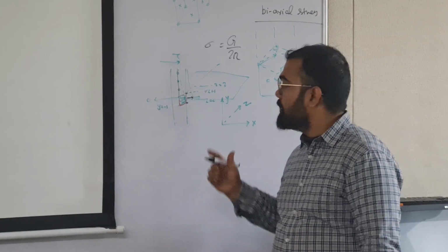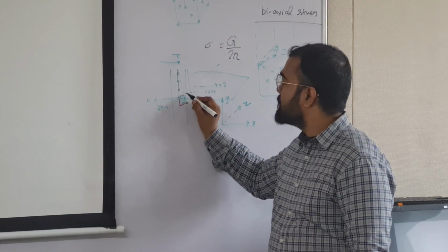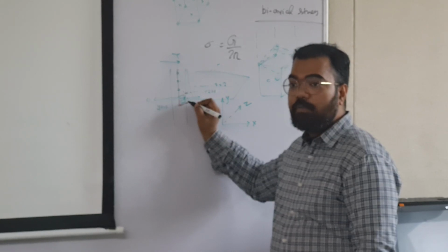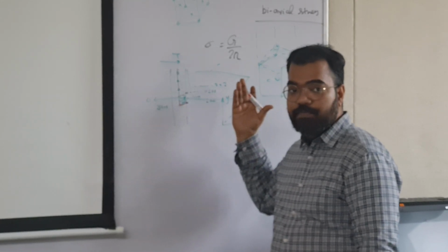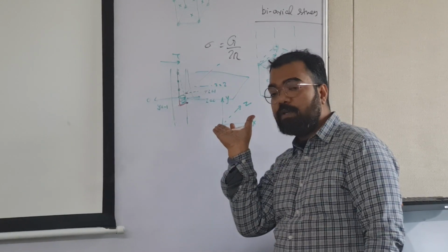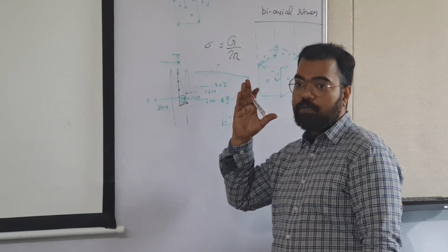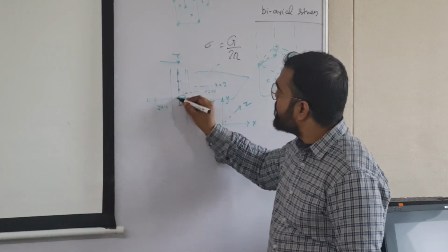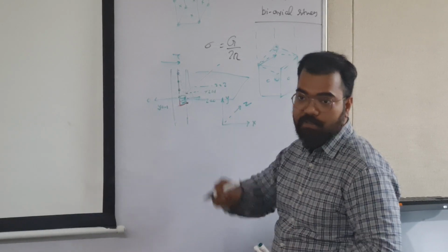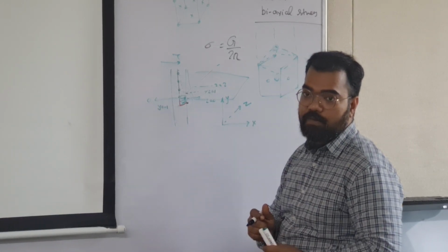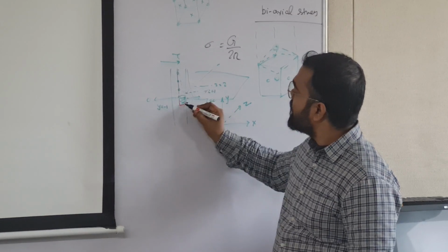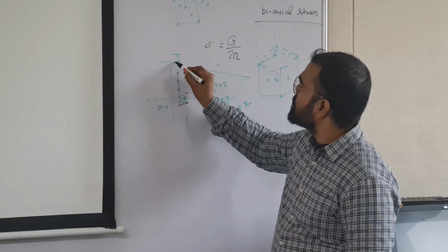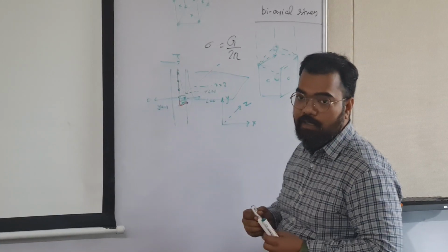Right? If this is the Burgers vector and this is the dislocation line, then it is still an edge dislocation. But the plane is not the slipping plane. The plane was that 1, 1, 1. Now it is perpendicular to that. So it is not possible for this thing to move. So now this part is pinned. This is nailed, crucified. And this phenomena will be happening at different locations. And you still are not stopping because why? Because you want to break the material.